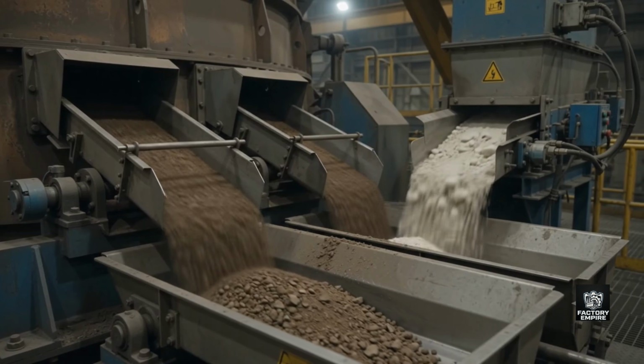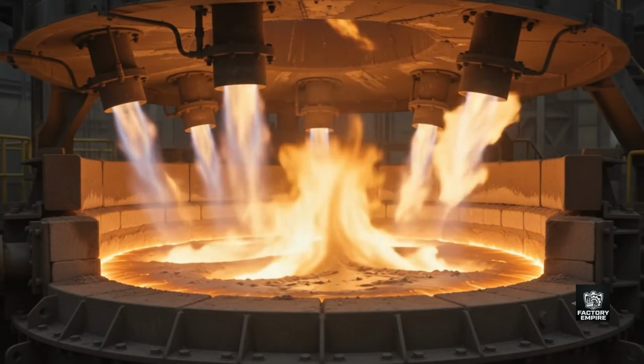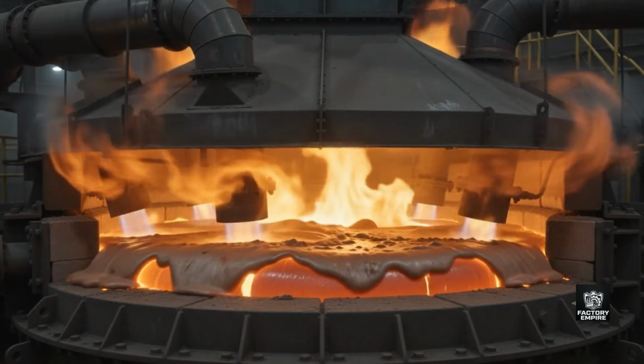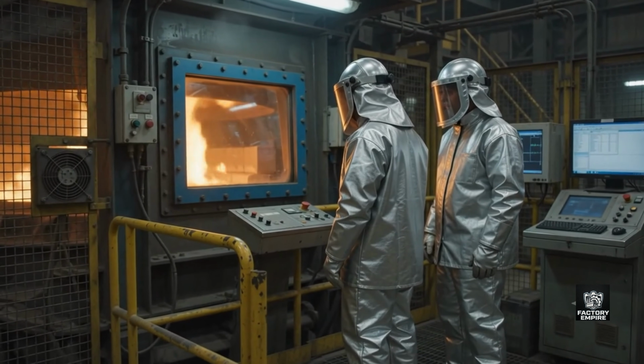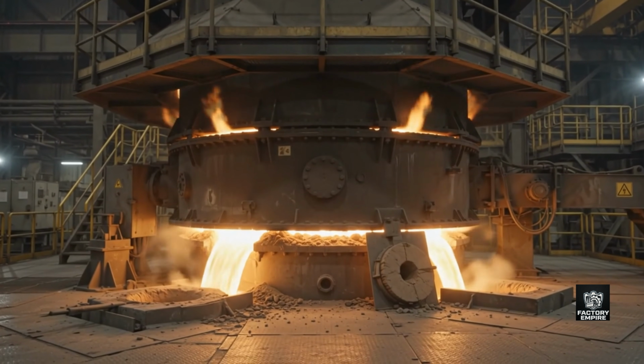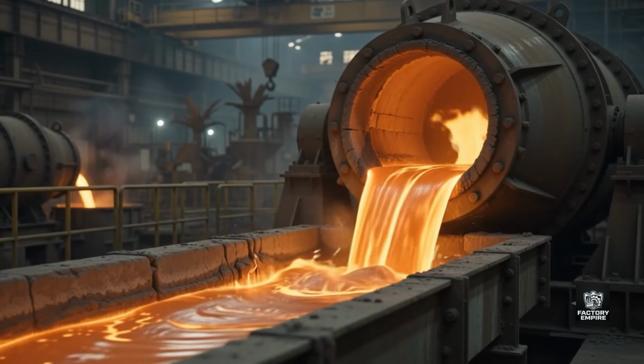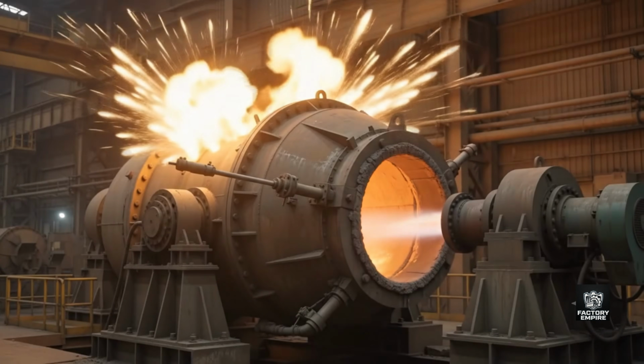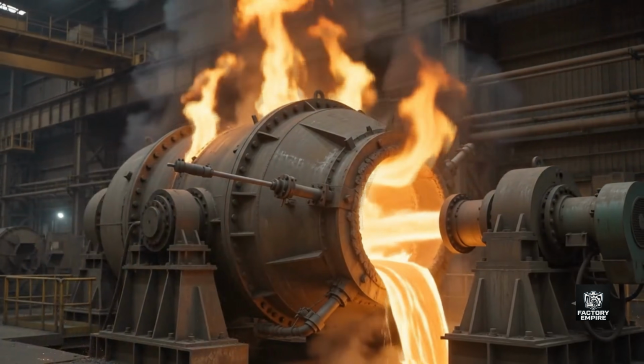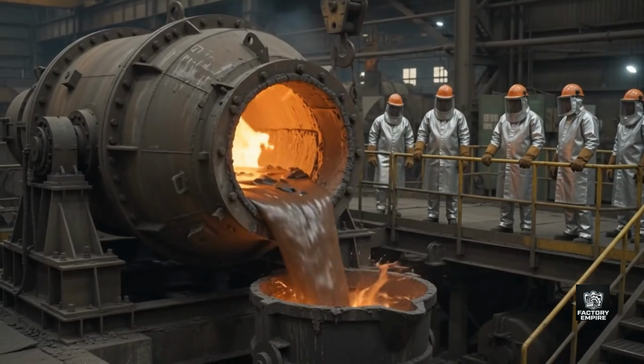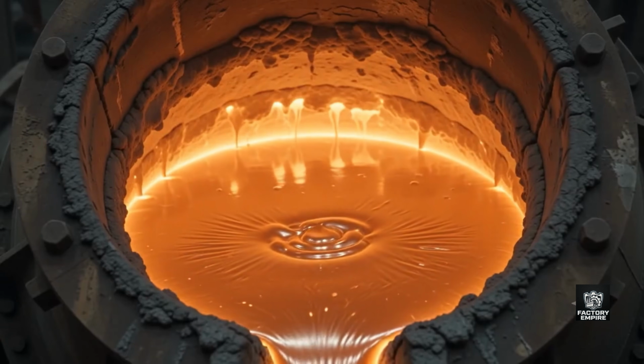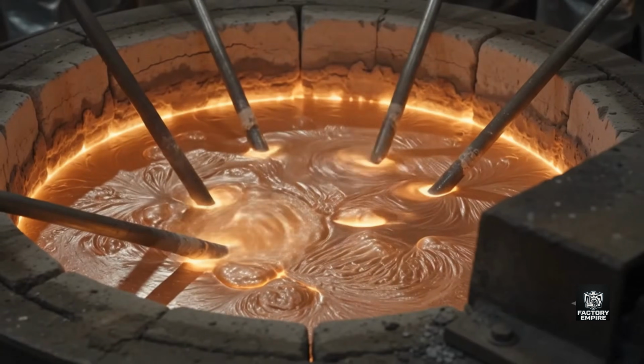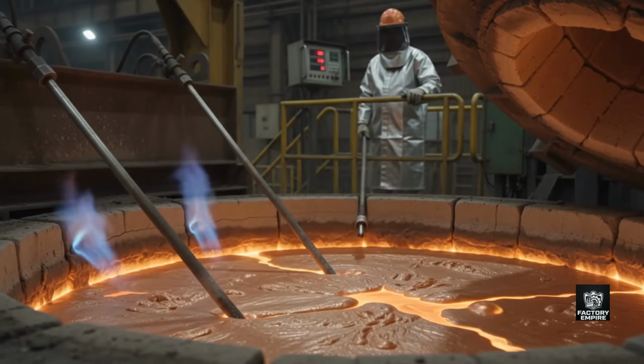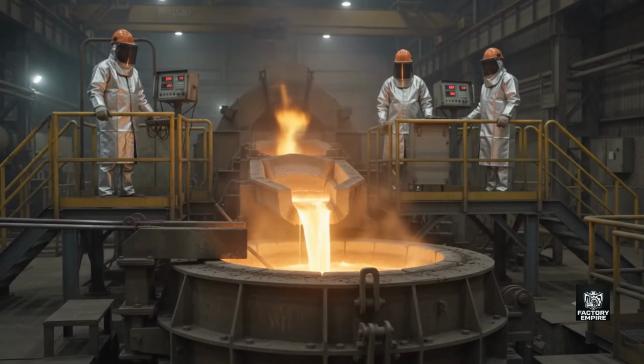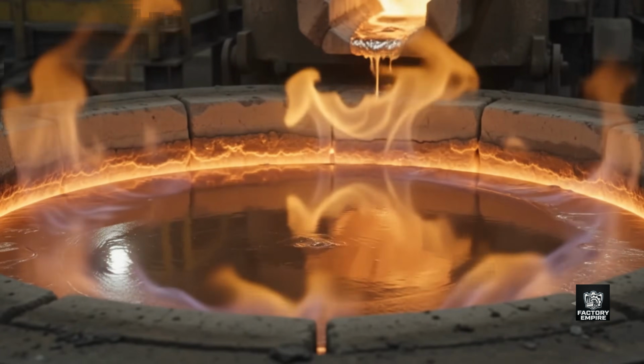The copper concentrate enters the flash smelting furnace. Oxygen and silica flux are added at temperatures above 1200 degrees, while sulfur gases are collected. The molten matte is transferred to the converter furnace. Oxygen is blown through the molten metal, removing the remaining sulfur and iron. After the slag is removed, the blister copper enters the anode refining furnace. Air removes the last remaining impurities, while natural gas eliminates excess oxygen.